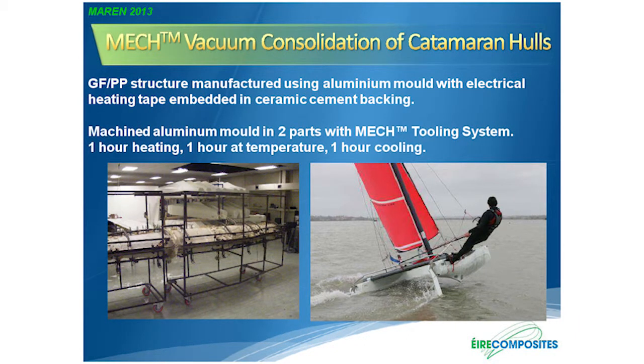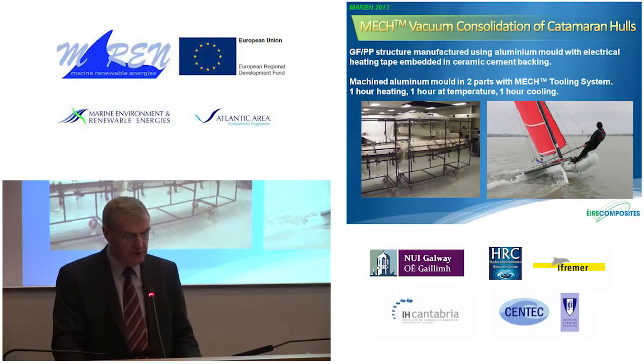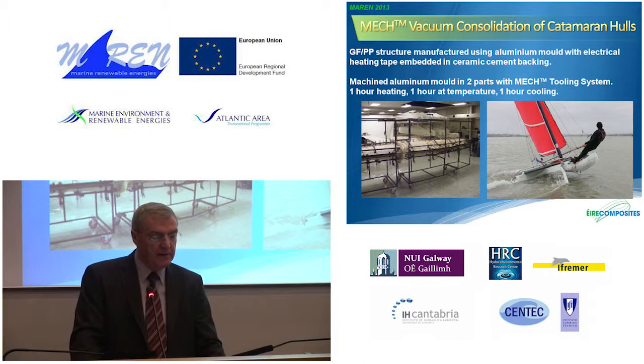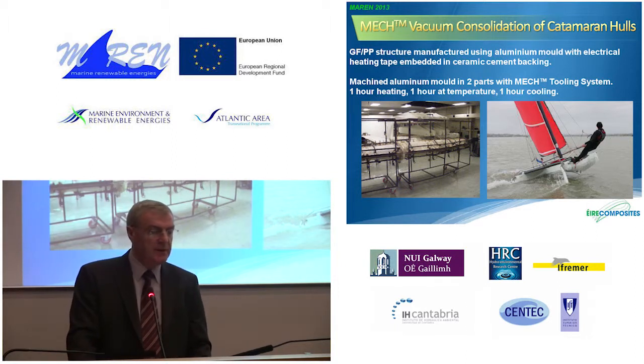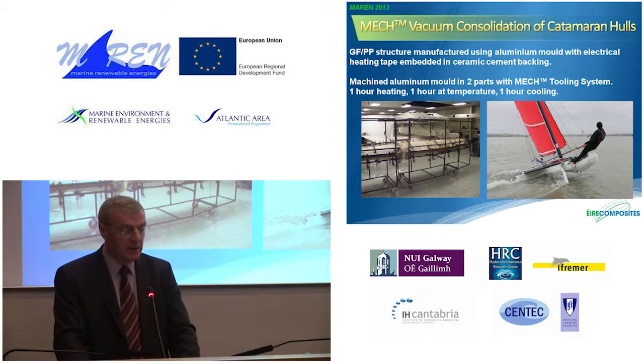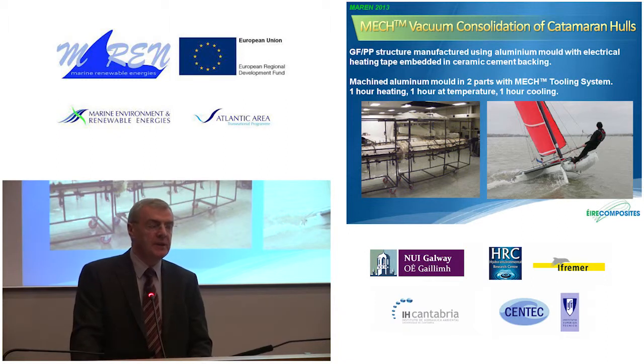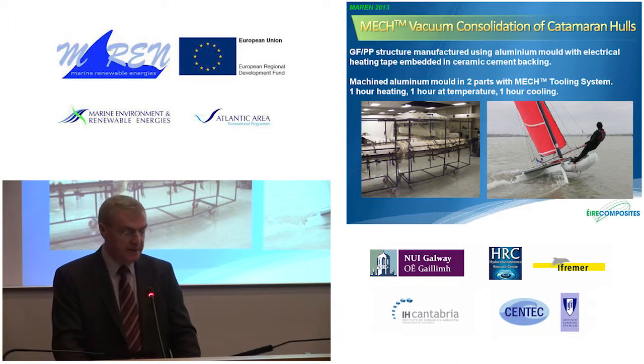This technology is currently being used to manufacture a number of composite parts, and the catamaran hull, which you see illustrated, is a 15-foot hull, which is produced using an aluminium mould in 2 parts, with a MECH tooling system on the B side of both those parts. The cycle time is typically 1 hour heating, 1 hour at temperature, and 1 hour cooling. The material we use is glass fiber reinforced polypropylene, and it's a very high impact material which is ideal for that type of product.